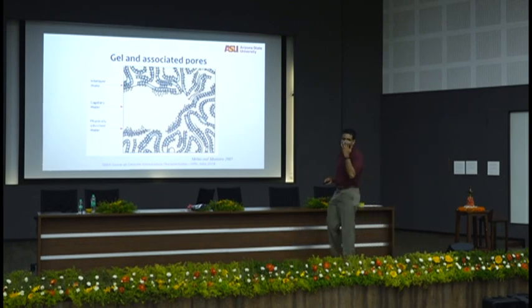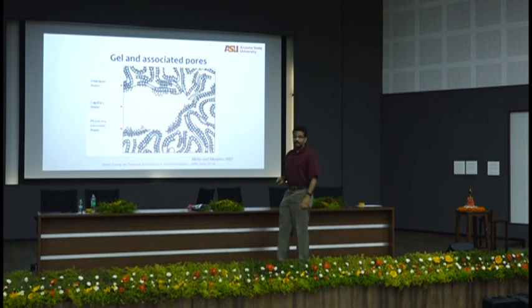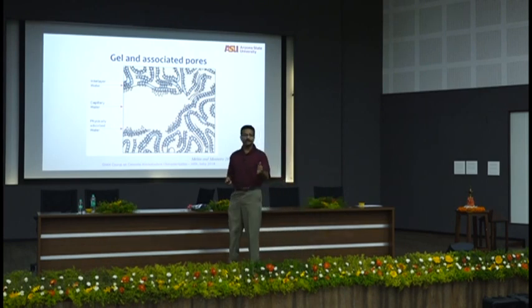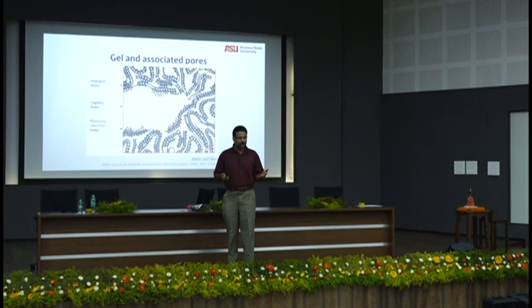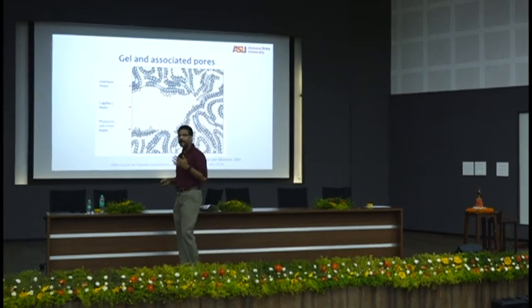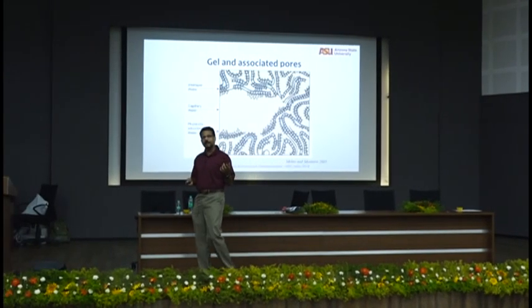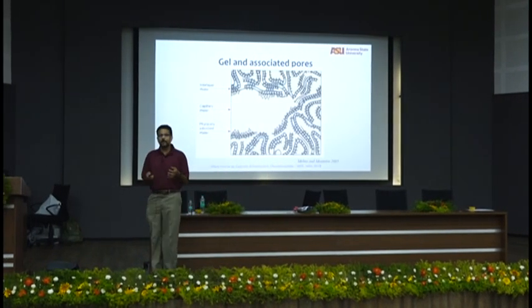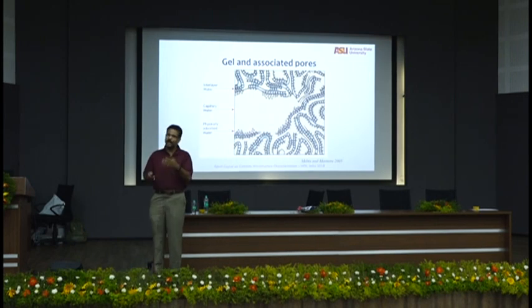And even in concrete textbooks, you will see gel pores are dry, drying of gel pores. I mean, gel pores should not be dried. Okay, interlayer water has to be there. I'm just calling it a gel pore because I'm calling the smallest pore gel pore, I'm okay with it. But if you're calling gel pore as the interlayer water, that's not correct. Get it?